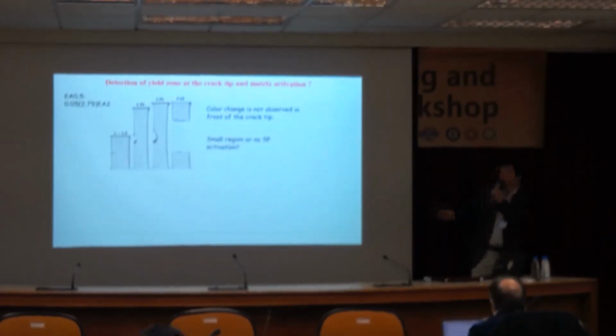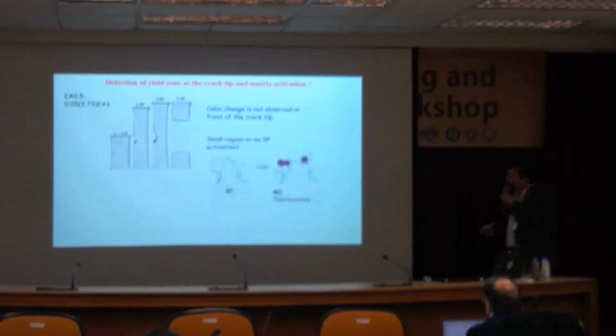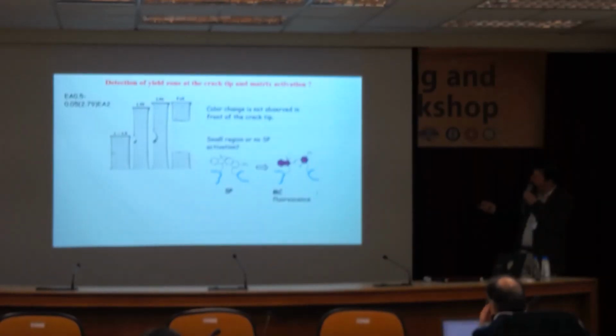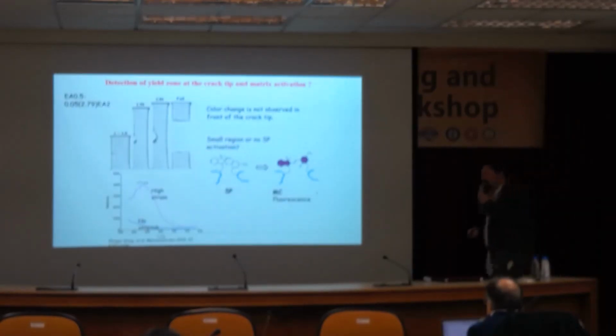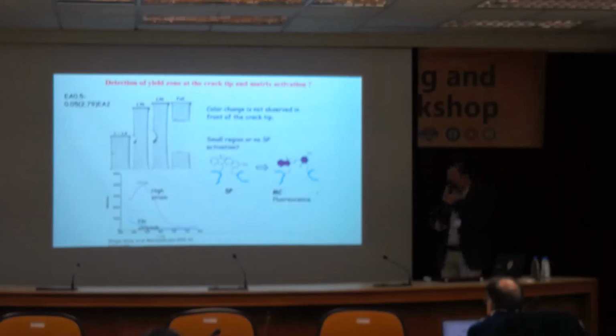So we were wondering, okay, is that because the region is too small? At this magnification, we can't see it. Or maybe it's not activated at all, and our hypothesis is wrong. So what we did is we actually took advantage of another property of spiropyran. It also gets fluorescent. So when you change from spiropyran here to merocyanine, this particular molecule has an emission in fluorescence, so around 620 nanometers. So it's possible to make observation with a microscope, a fluorescent microscope.